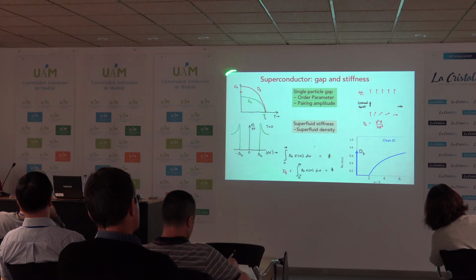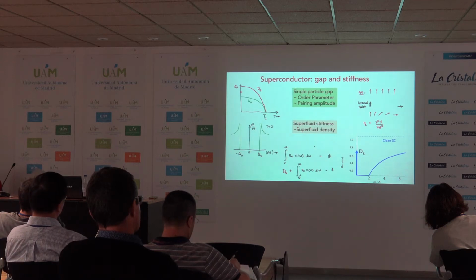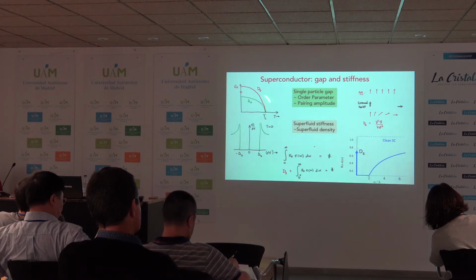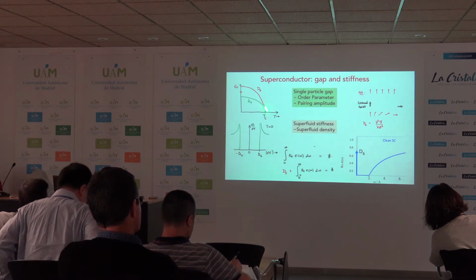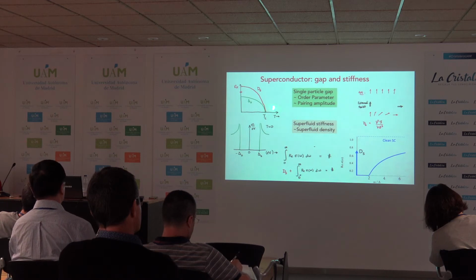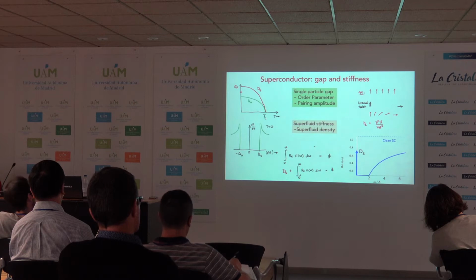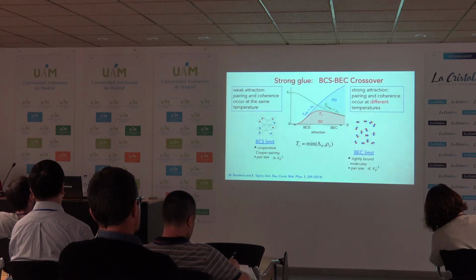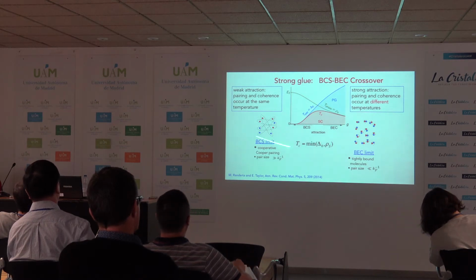And in general, the gaps are very small, on the order of milli-eV. The superfluid stiffness is a very large energy scale. For aluminum, for example, it's on the order of EF. But as you increase the temperature, both scales vanish simultaneously at Tc. And that's the transition.